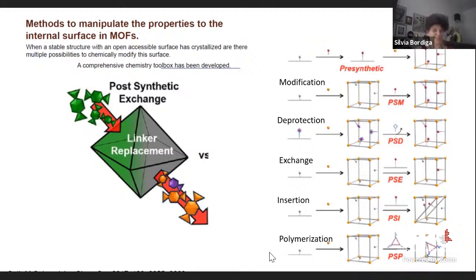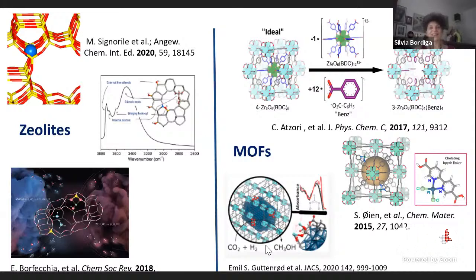And so these are very nice drawings, but sometimes it's very difficult to control in practice the appropriate procedure to obtain the wished material. So just to conclude, I've shown some examples where we can play with zeolites and metal organic frameworks, guiding the formation of local defects, introducing ligands that at the end can insert also a specific species, for instance, in this case, a platinum ion. And then these materials can be modified also to include metal particles, playing with the synergy effect of having the cages of the MOF in combination with the metal particles.